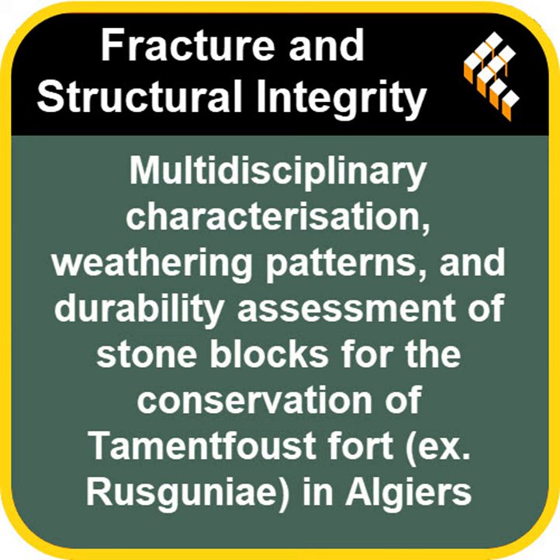The test on that porous T1 limestone, even though it only lost a tiny bit of mass, 0.65%, sounds durable. Superficially, yes, but those heating and drying cycles drastically accelerated internal damage. The internal pressure weakened its compressive strength significantly. So it looks okay on the surface, but it's crumbling inside. Precisely. That high porosity, over 30%, makes T1 incredibly vulnerable to this hidden attack. A silent killer for the stone.